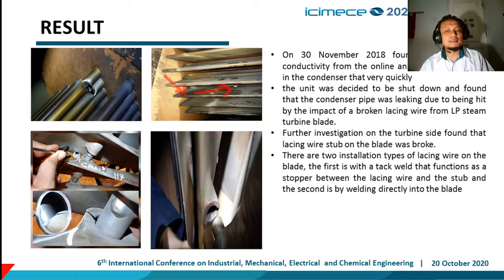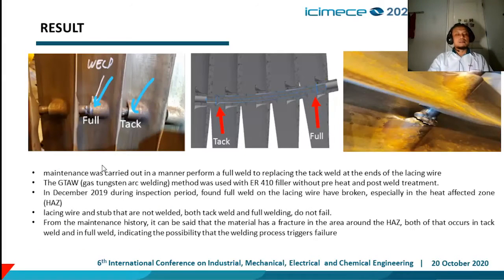There are two installation types of lacing wire on the blade. The first is with the tack weld that functions as a stopper between the lacing wire and stub, and the second is by welding directly into the blade. So this is how we do maintenance. Maintenance was carried out by performing full weld to replace the tack weld at the end of the lacing wire. The welding method is using filler ER410 without preheat and post-weld heat treatment.